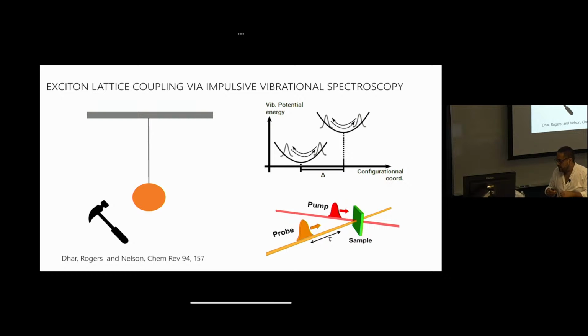So that's the experiment. But now if you've got a system in which the electrons are coupled strongly to phonons, you impulsively excite the electrons. You inject electrons in the conduction band impulsively. That's like you've got a pendulum, an oscillator. You hit it very quickly and very hard with a hammer, but you don't hit one. You've had the ensemble of pendula that you hit very, very impulsively with a hammer, and they all start oscillating in phase. So you inject electrons in the conduction band.